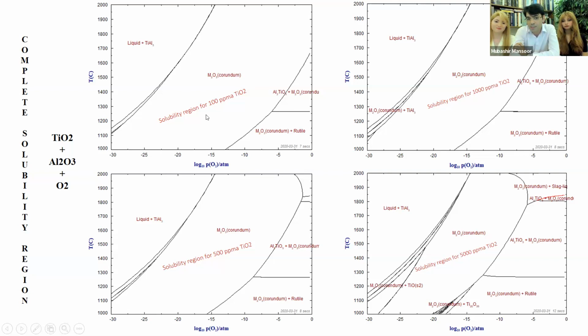But as you increase the titania concentration to, let's say, 500 parts per million, then you can never reach full solubility. So that's the reason why, I have heard this many times, and we have also experienced this ourselves from sapphire enthusiasts, that, for example, they take a sapphire, they do the heat treatment in air, and they say, I cannot get rid of that rutile. Well, no doubt, if you have too much rutile in there, you need to play with the oxygen in your furnace. Otherwise, it's impossible to dissolve it all. But the moment you reduce your oxygen concentration by even a little bit, you get full solubility. So it's an essential part of the process.